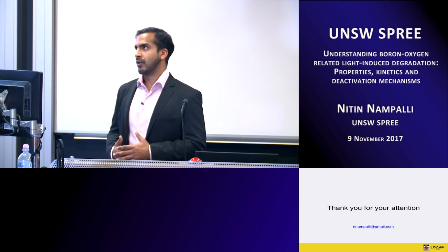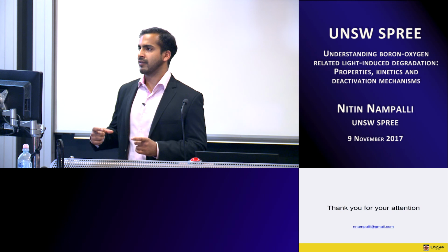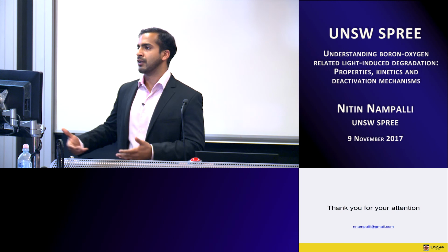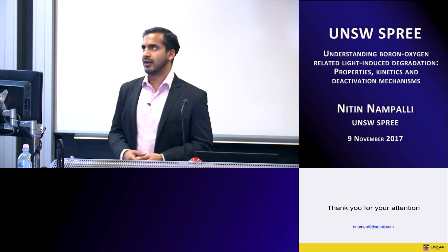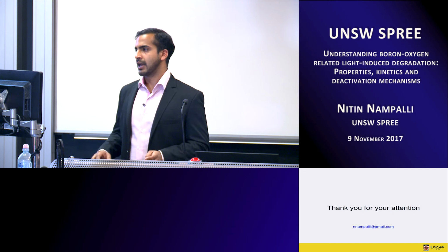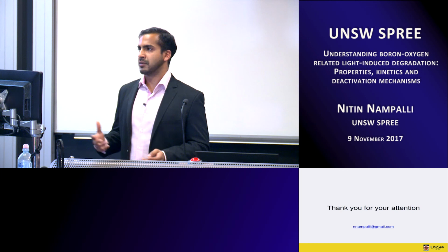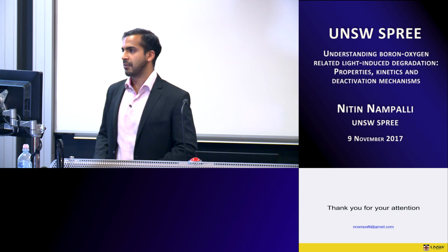Also, the absolute lifetimes weren't making a lot of sense. So in spite of dark annealing the wafers, they didn't completely go back. They weren't quite flat. So there was some other SRH defect in there. And also there's been other evidence of this firing activated defect in CZ. And there's talk about how it's actually similar to the multi CID defect, or it could even be the same thing. So you mean metal related?